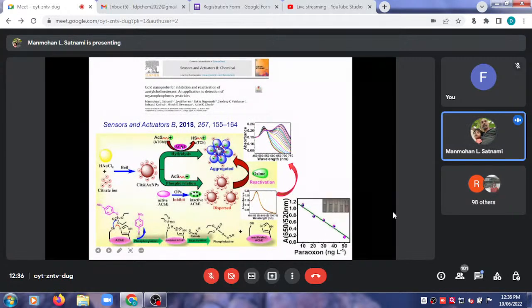Now it will not catalyze the hydrolysis of acetylcholine, and if it will not hydrolyze, then the sulfur group will not bind with the gold nanoparticle, aggregation will not happen, and the color will remain red. See the red color, and it will give absorbance at 520 nanometer. Then further what we did, since the enzyme acetylcholinesterase is inhibited, we added some reactivators.